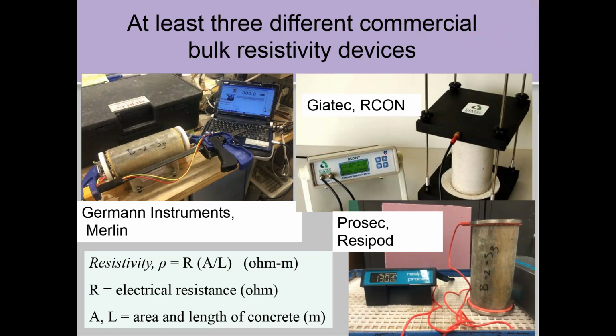You basically get the same information as that test that took a whole day. So it makes it much cheaper. There's at least 3 commercial suppliers. I think there's more, but these are 3. Germann Instruments has one. And they use a carpenter's clamp to clamp the electrodes in place to get good contact between the electrodes and the cylinder. Giatec out of Ottawa uses one where they have 2 electrodes with sponges on the ends, and they clamp the ends down, or you can throw a weight on top. And ProSec has one too, again with the electrodes on top and bottom with some wet sponges. It needs a weight on top to get enough contact.